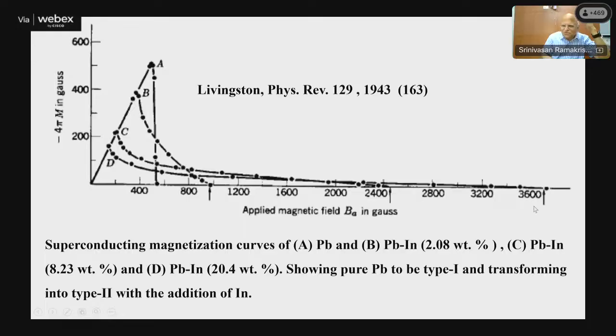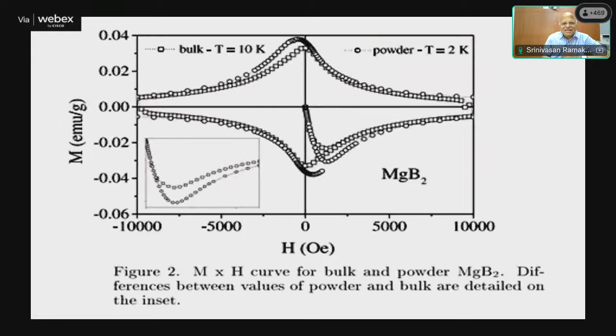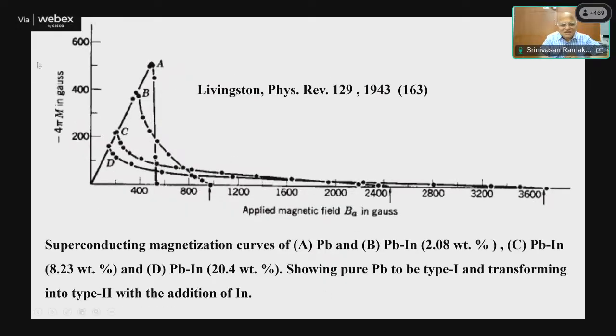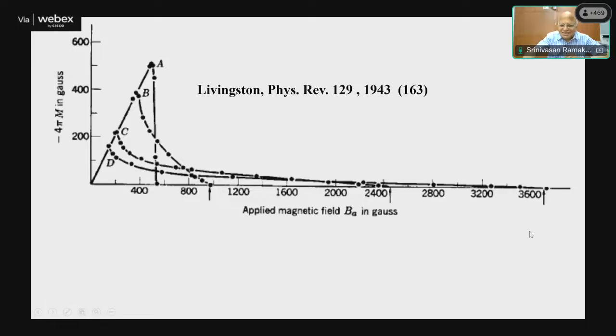So the upper critical field is close to 3600 Gauss, whereas the lower critical field is extremely small, maybe about 100 Gauss or so. This experiment clearly showed how the magnetic properties change as a function of indium concentration, as pure lead goes from type 1 to type 2 superconductivity, which could be easily explained by Ginzburg-Landau. Of course, if you have defects and disorder in the system, the magnetization is not going to behave as smoothly as this. The pinning will make it completely different.